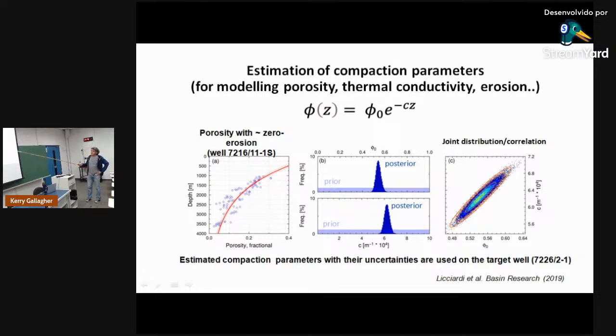And also those 2 parameters are correlated. So this is the surface porosity phi 0 against the compaction constant C. We see they're very strongly correlated. Okay, so we can change one of these, and provided we change the other one to respect this correlation, we'd get much the same effect. Okay, but we've defined what these parameters are rather than just taking one value for each. We're saying let's use this information, let's use the probability, such as the posterior, when we're modeling somewhere else. Okay, so we took another well, this is the well which was, I can't remember,